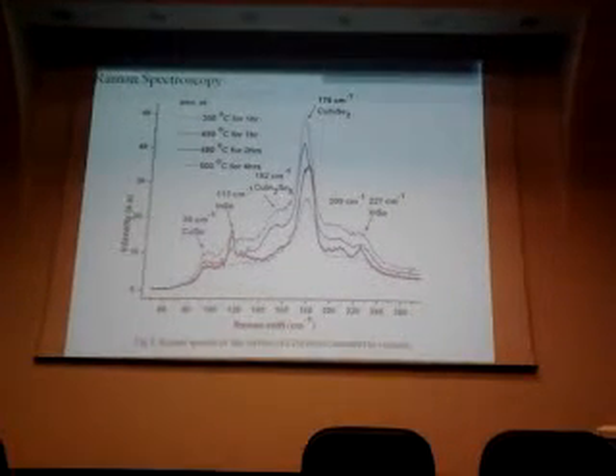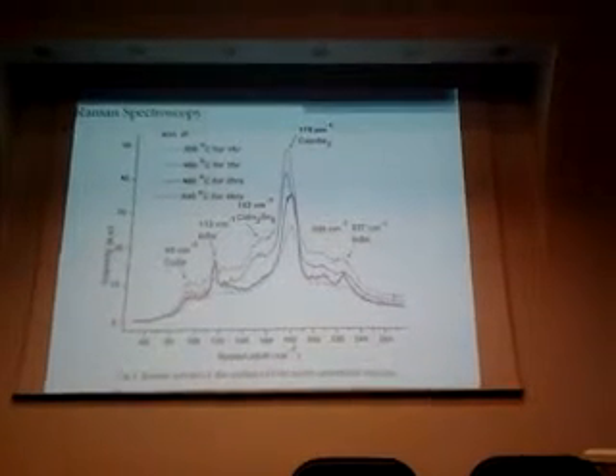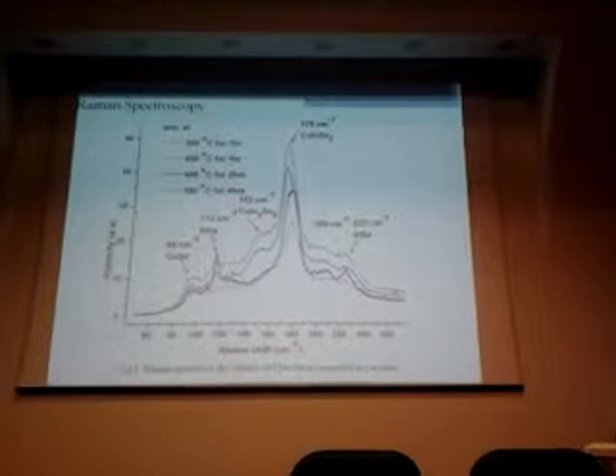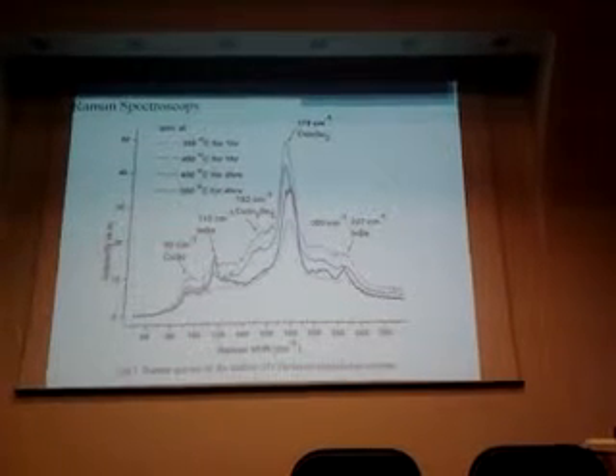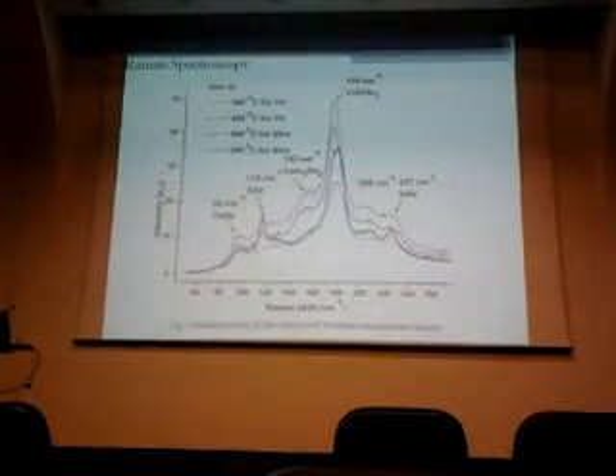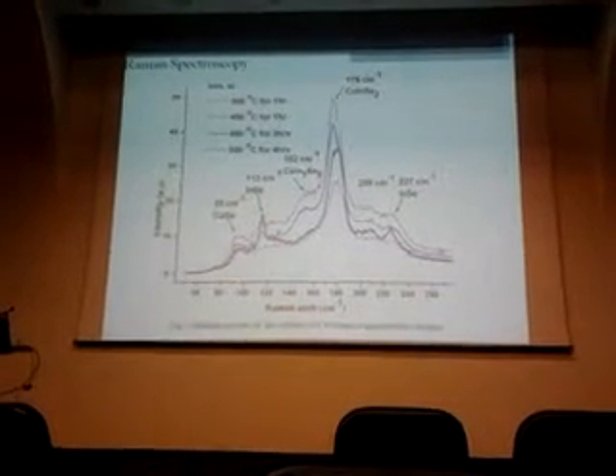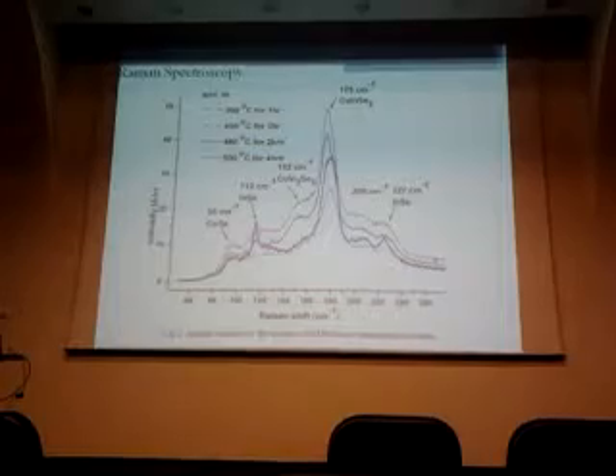We can also see some trace amount of copper indium 3 selenium 5 around 152 per cm, and also some copper selenide and indium selenide at 95 and 130 per cm. We conclude from the surface Raman that the prepared structure at the surface is not purely copper indium 3 selenium 5, but is a mixture of phases.